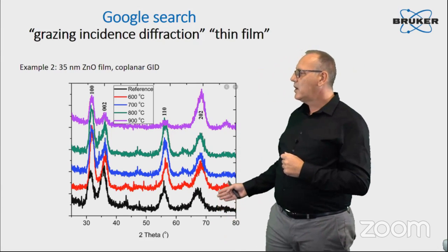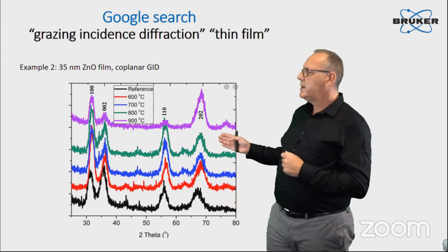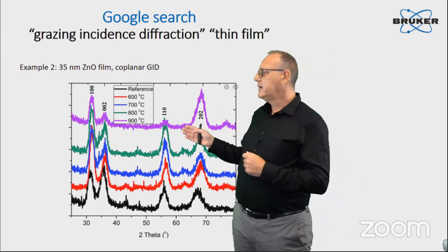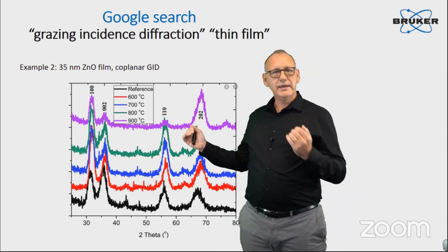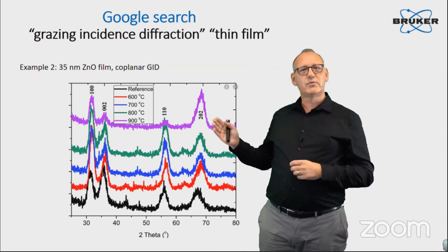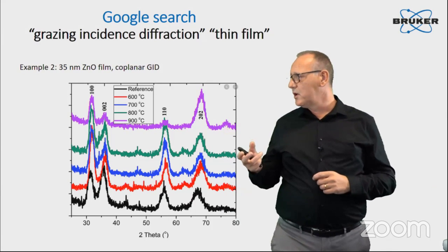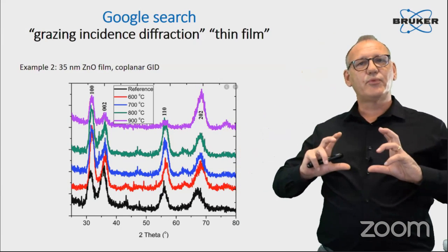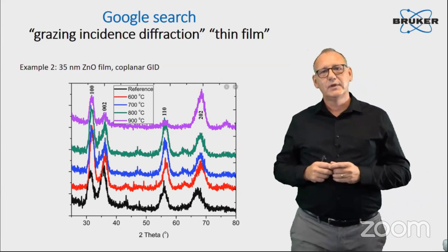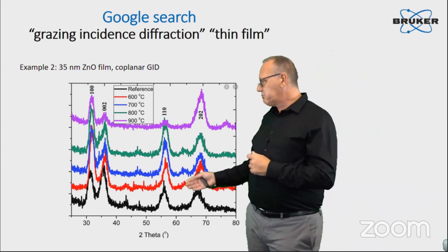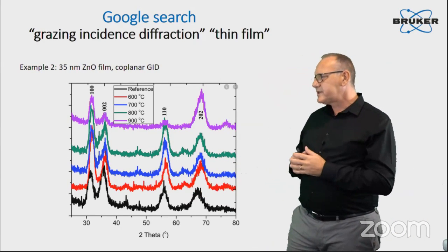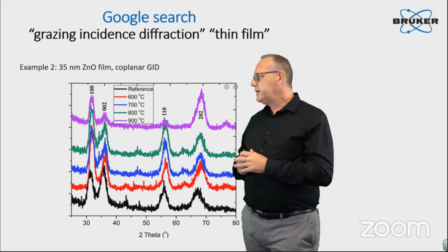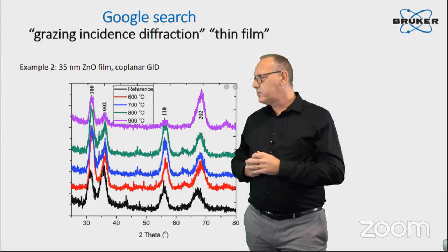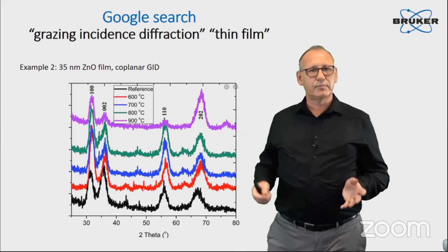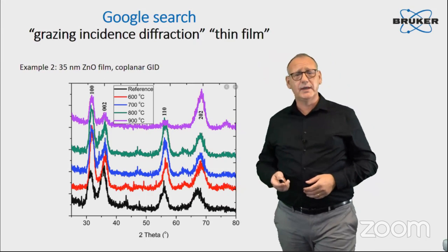And by heating, you see clearly some change in the peak intensity. Right? So the peak intensity ratio is changing from reflection to reflection, which is an indication of a change in the preferred orientation of the grain. Again, you could say, well, maybe the step size is too small, maybe it's a bit noisy, but for what it was supposed to do, it did the job. So what's my point here?